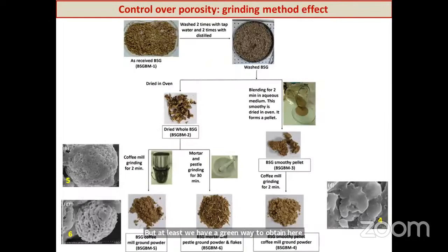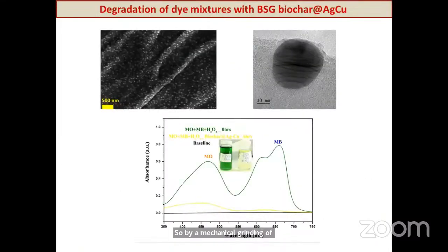And finally, you can see this is a brewer spent grain using mortar and pestle, and we can have a porous structure that we cannot obtain if we, for example, use a coffee mill or a blender. We tried with a blender from a local shop. Mechanochemistry should provide not only porous structure but also some graphitization of the biochar. So this is another green way to obtain a porous structure of the biochar, by mechanical grinding of the initial biomass.